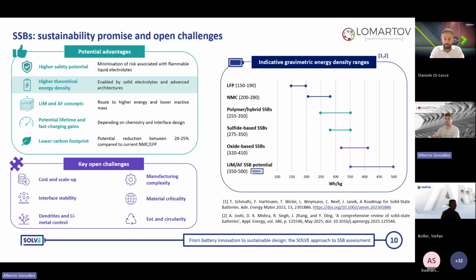Manufacturing complexity is also another major point. Solid-state batteries require very good control of layer thickness, pressure, defects, interfaces, and processing conditions. And this makes scale-up more challenging than simply replacing one material in a conventional battery line. Finally, material criticality and end of life also remain open questions. SSBs may reduce some impacts, but they can also introduce new materials, new coatings, solid electrolyte formulations, or fluorinated components that need to be addressed carefully. And also the recycling routes are less mature than in the case of conventional lithium-ion batteries.